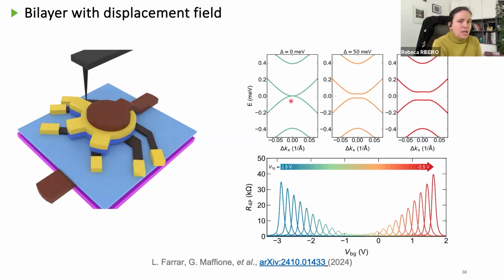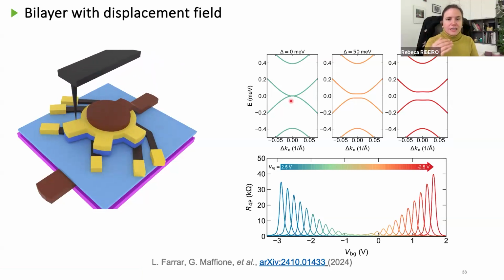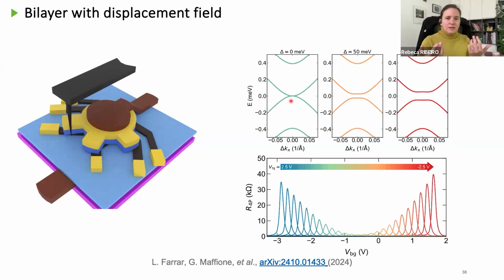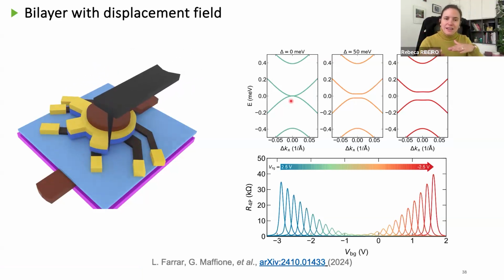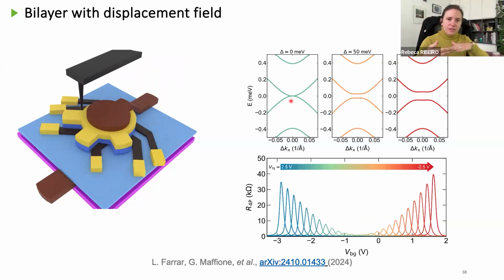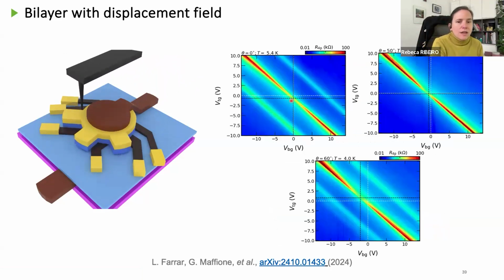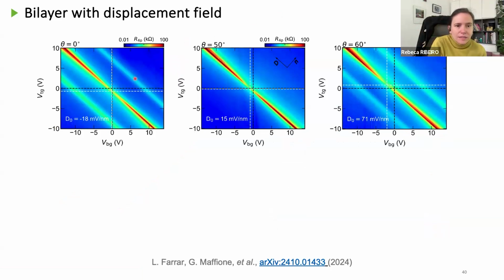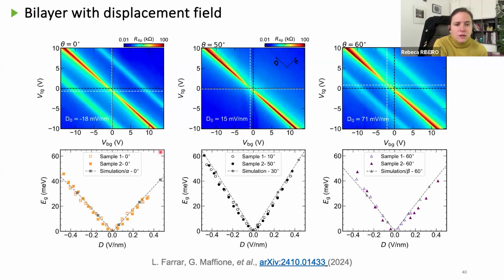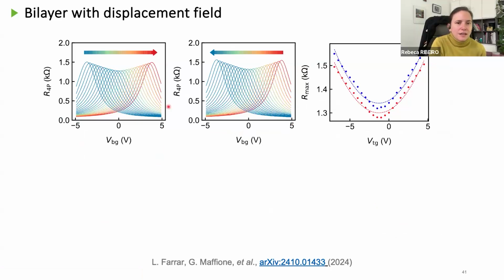And at this position is in fact where graphene is really in its natural state, which means that there is no remnant electrical field created by the van der Waals forces. Okay, so you can see that for these three, it's already different. You don't have the same position for the three of them. Here you have the value of this intrinsic displacement field, and you can see it varies a lot from one alignment to the other. So I'm just gonna skip this for a second because it's gonna be confusing if I say it here. And I'm just gonna remind you what I'm doing.